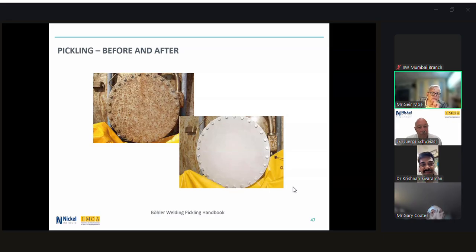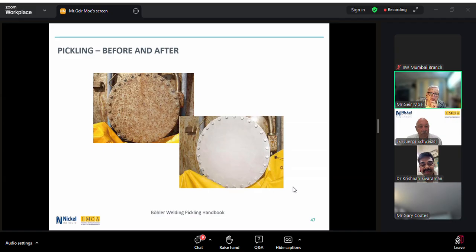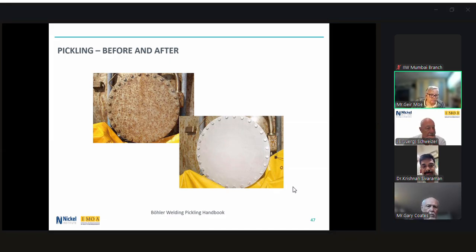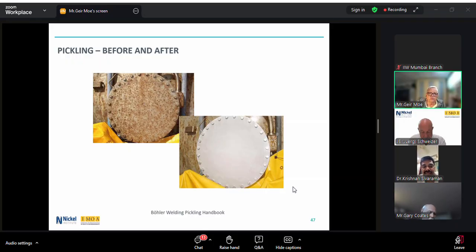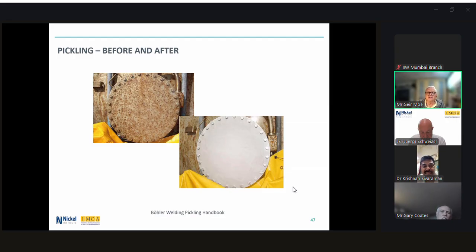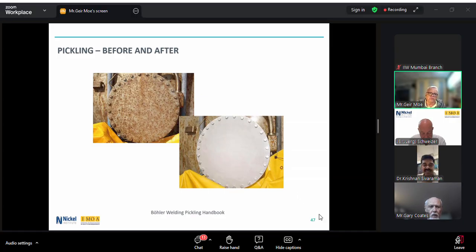Well, yes. Well, all stainless steels, if the surface has been contaminated, whether it's after annealing and you have formed annealing scale, or heat tint from welding, or if there's contamination, iron contamination on the surface because of some carbon steel fabrication that was performed adjacent to the stainless steel, you always want to restore the stainless steel to its original clean surface, and pickling will remove heat tint and annealing scale. And then when you rinse it with clean potable water, you allow the clean stainless steel surface to spontaneously form its protective